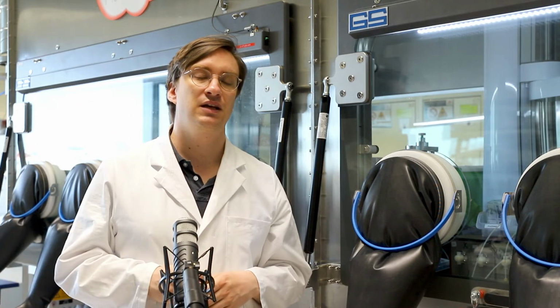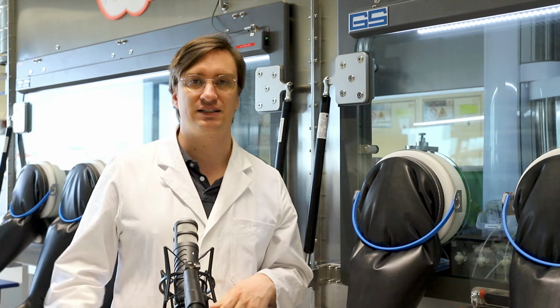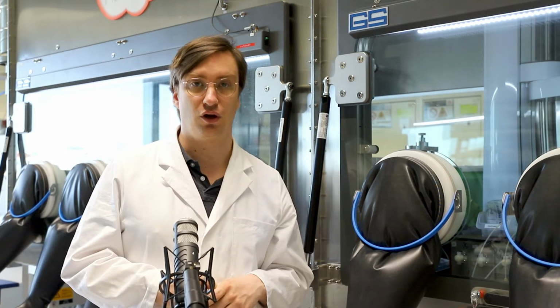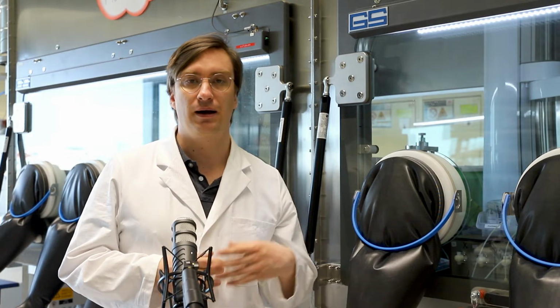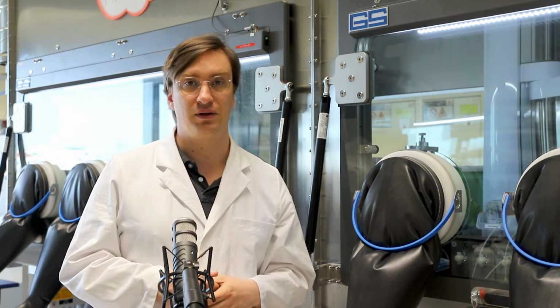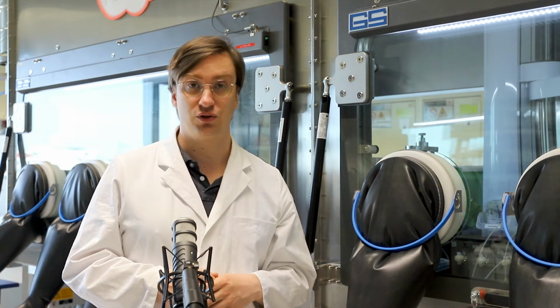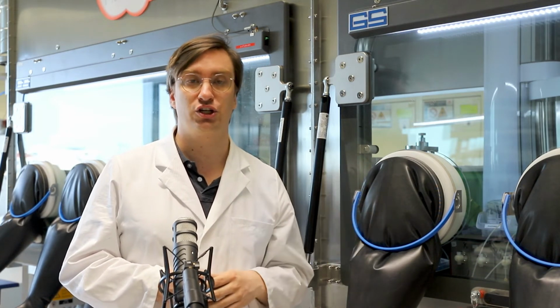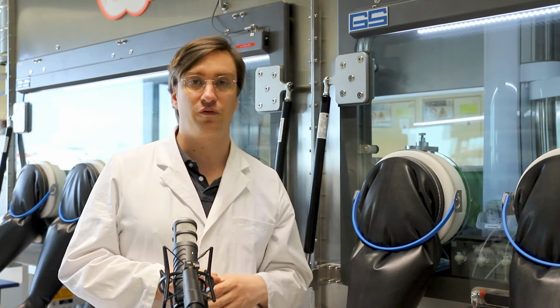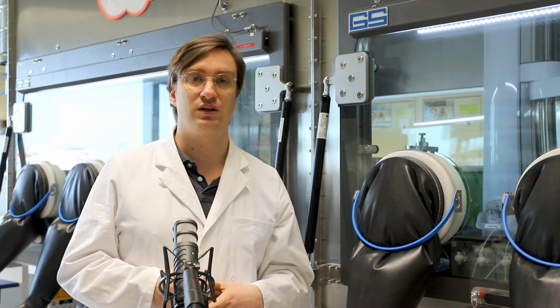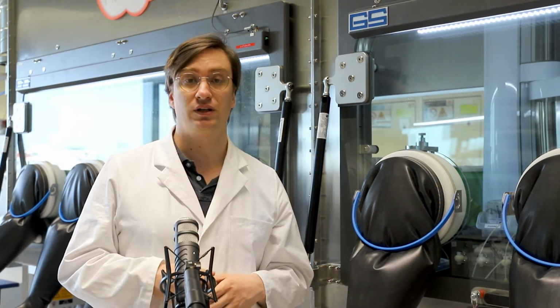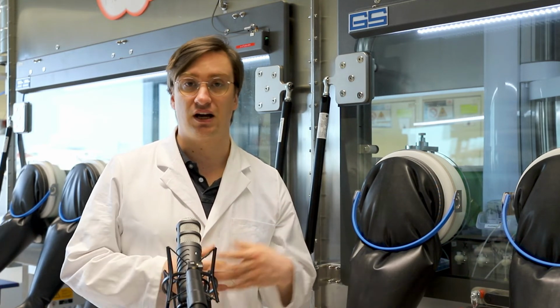We have an alternative system from the hardware and software exactly the same, but it's housed in an argon-filled glove box. So there we can also investigate metallic anodes or very complicated systems that might react with nitrogen. In here, the system we actually demonstrated before to be capable of active learning. So active learning means that we can, for instance, change parameters during the experiment or the formulation to optimize for a certain property. For instance, we can try to go to your sample, measure at different positions, and try to optimize the electrolyte for some SEI resistance after we applied some potential.